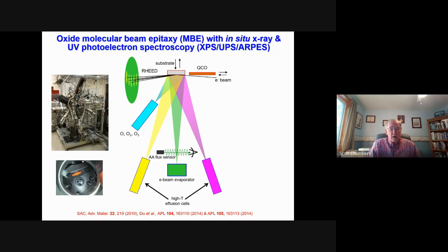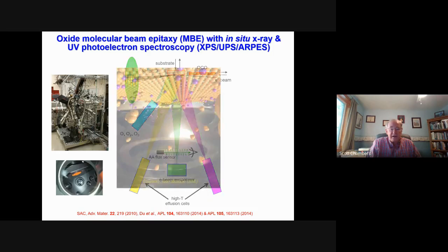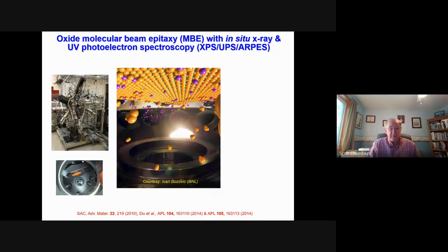And this is our workhorse for oxides right now. It's got a number of effusion cells and electron beam evaporators for metals. And then it has a couple different oxygen sources we can plug in. And here's a cute little artist's conception of the MBE process going on, where you have the individual atoms and molecules, in this case ozone, coming up from the sources below onto a substrate. The substrate's hot, you nucleate, you can make a new material literally one atomic layer at a time.